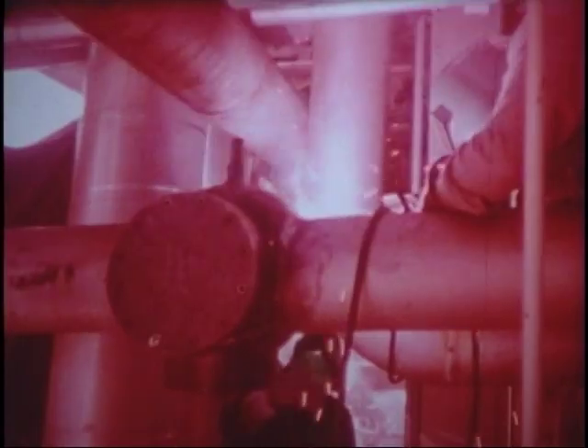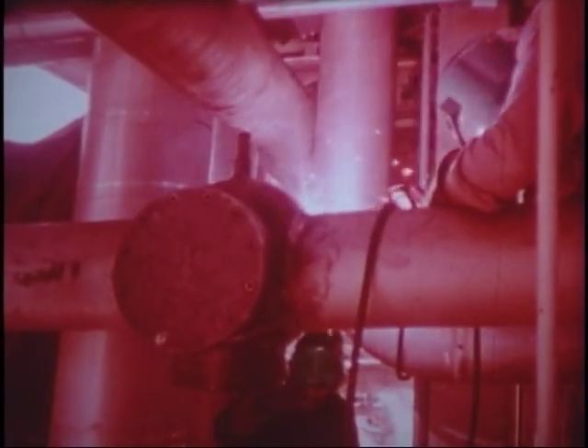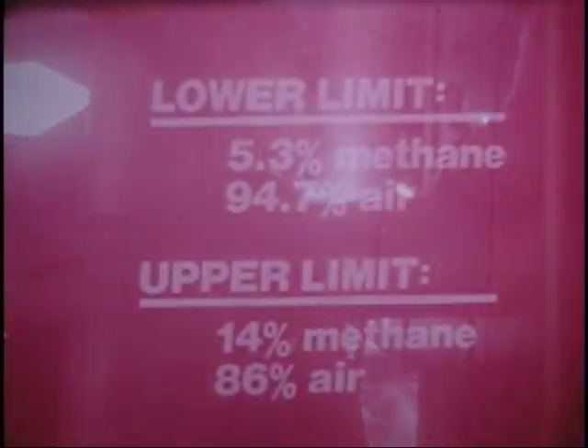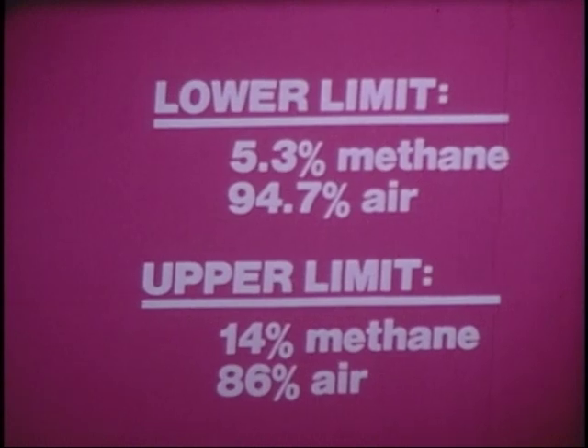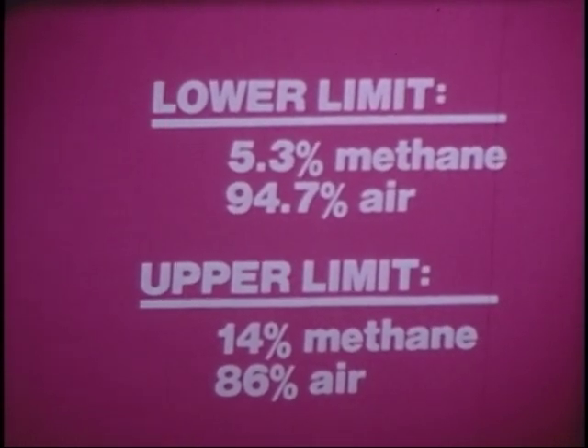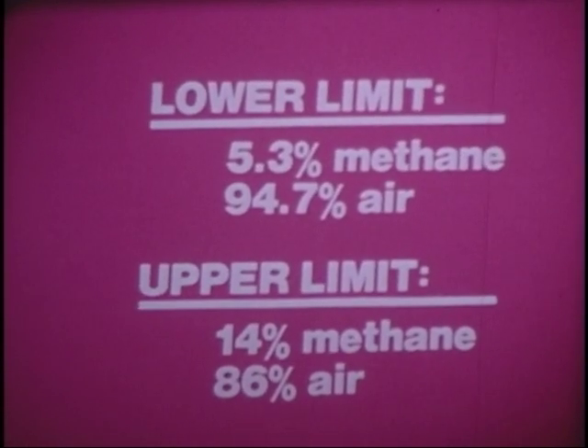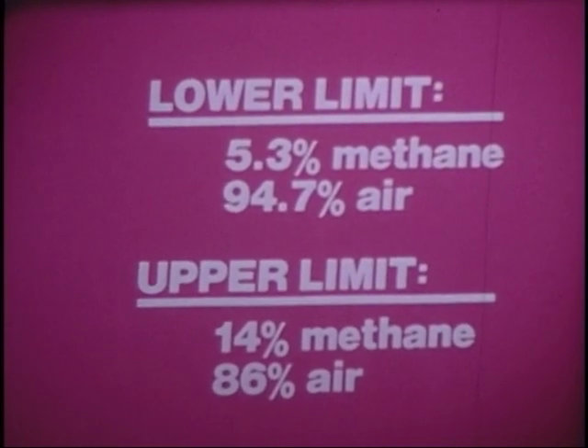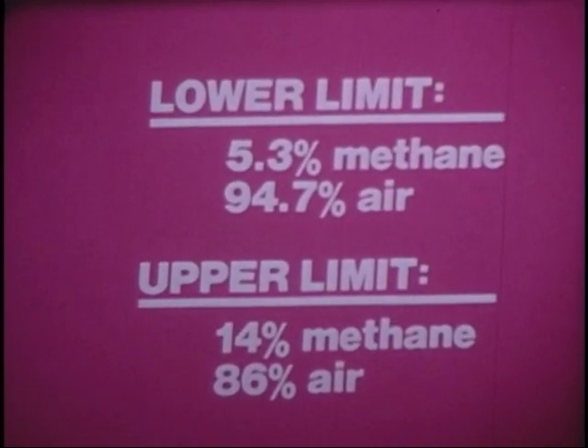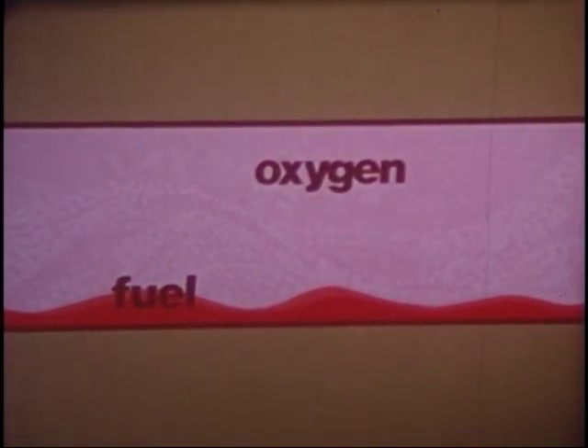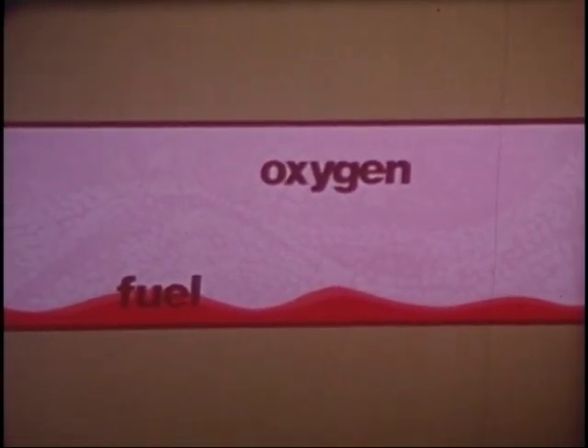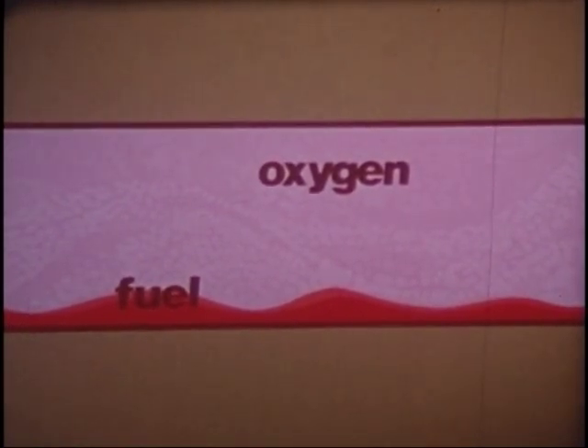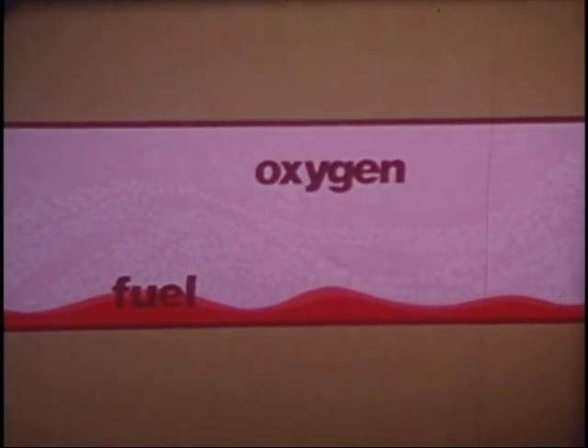Welding on pipe with unstable contents should be avoided. A mixture, such as oxygen and fuel, with a mixture in the combustible range should not be welded on. A weld can be made on the line if the fuel component of the mixture is increased to give a mix that is too rich and is not in the combustible range. Welding should not be done on oxygen, oxygen-enriched air, or compressed air lines if there is any possibility of a fuel being present.